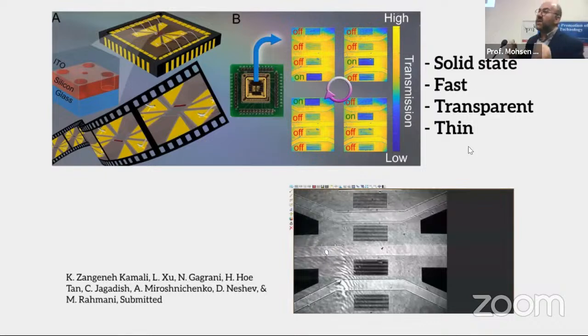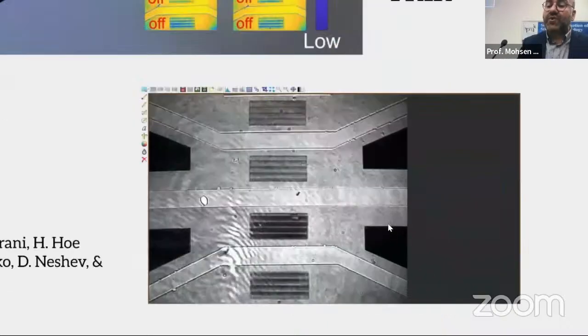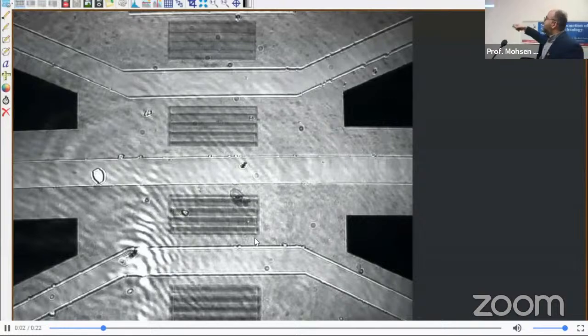They cannot be so small, because these liquid crystals use actual liquid. You need the liquid, and those liquid cells are suspended. By applying a field, you can rotate them so that they work as a switch to turn the light on and off. But here, we don't need any of those barriers. I'm not going to go into too much detail, but what I'm trying to tell you is that this technology can increase the resolution of the displays we have by 100 times. And more importantly, it can help us save 50% of the power consumption, because it's a completely different technology. It's not liquid crystals. It doesn't need polarized light, so it saves 50% of the light. So you can see these pixels we have made, and you see that we can turn them on and off on demand.